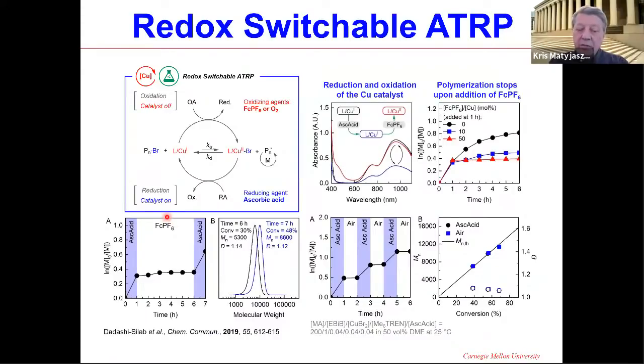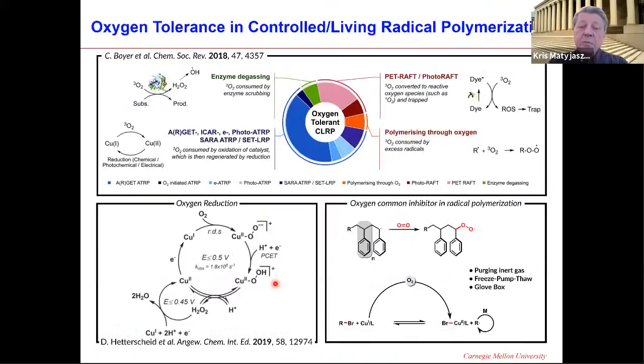like ferrocenium cations. So again, ascorbic acid promotes polymerization, then ferrocenium ion stops, and then we can add more ascorbic acid and the reaction continues. Or you could do the same with ascorbic acid and air. Ascorbic acid, and then stop. You can put more ascorbic acid, it starts. Oxygen stops. And in fact, all of these polymerizations are well controlled because you do not kill chains, but rather you kill the catalysts or activators, if you wish. So this is an interesting possibility.